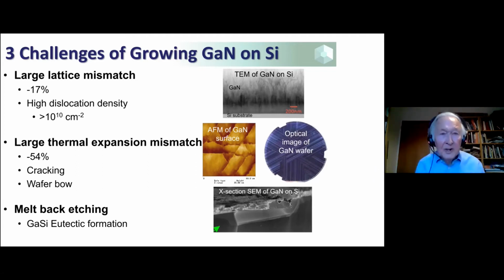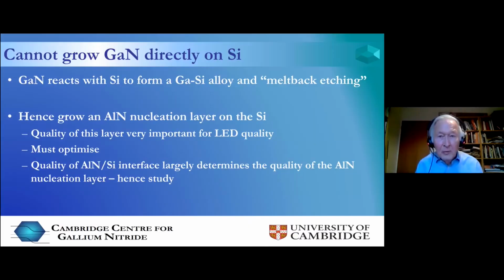So how did we overcome the problem of this melt back etching and the formation of a gallium silicon alloy? So what we did was to introduce a different material, aluminium nitride, which you can grow on silicon, and that formed an intermediate layer, a nucleation layer on the silicon. And the quality of that layer was really important for the final LED quality. You had to optimize it. And the quality of the aluminium nitride on silicon interface largely determines the quality of the nucleation layer and then of the LED.